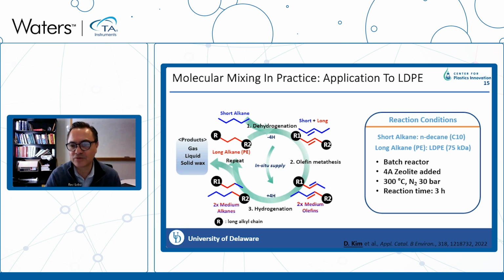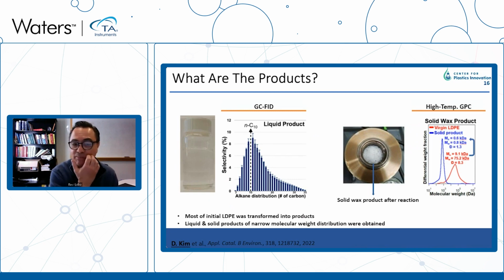Again, this is in a batch reactor, and the presence of the zeolite is very important to have a successful reaction. And these are the products. Here you can see the liquids that are obtained, and this is from gas chromatography. In this particular case, we use decane as our sacrificial solvent, so the molecular weight of the products that we obtain is centered around this alkane. You can see that the products are completely transparent and that we have what we can measure in GC, which is up to carbon numbers of 36. We don't react, at least under these conditions, all the polyethylene. We react about 80%, and we retain about 20%, which is solid once the temperature is reduced.